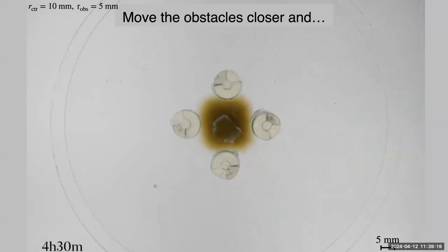But I think you'll agree with me that something much more interesting happens if we move the obstacles a little bit closer together. So now I'm showing you the same exact video. The obstacles are just a little closer. I'll speed it up a little bit. If you haven't noticed, these occur over very long times. They're not fast processes. And now if you direct your attention to the top right, you'll see a crack forms. And the hydrogel will tear itself apart. It will have this very dramatic multi-stage fracturing process. So this was really exciting to us because we set out to study swelling-induced stresses. And this is pretty dramatic evidence that there are significant swelling-induced stresses that build up in the system. It's possible it has implications for other applications of hydrogels. And folks who have worked with hydrogels in the lab are not terribly surprised by this since these materials can be very brittle. But this is a really nice platform where we can study that systematically and specifically the contribution from this dynamic swelling process itself.